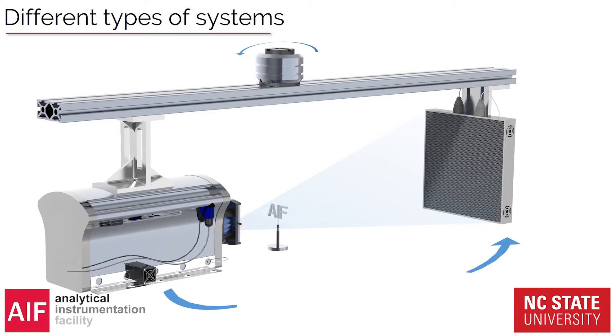If you spin your sample very fast it will move around, and the sample cannot move during a CT scan, so we resort to rotating the equipment instead. This is used today in novel systems called 4D systems, where the '4' stands for resolving time. We can do a complete scan in one to two seconds. When you make scans that fast, you can get a progression through time when looking at the volumes of your samples — you can see how something is developing, how fluid travels through a foam for example.